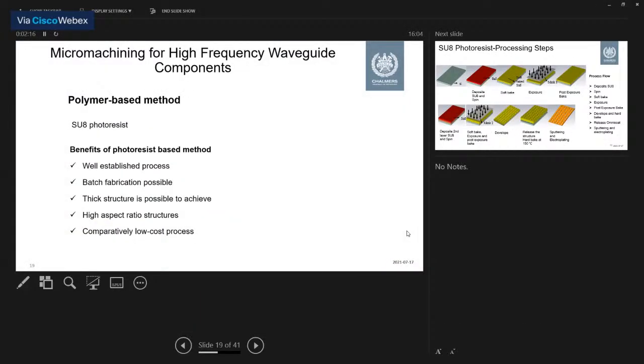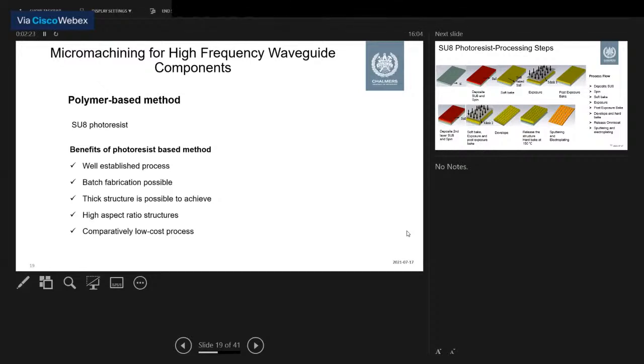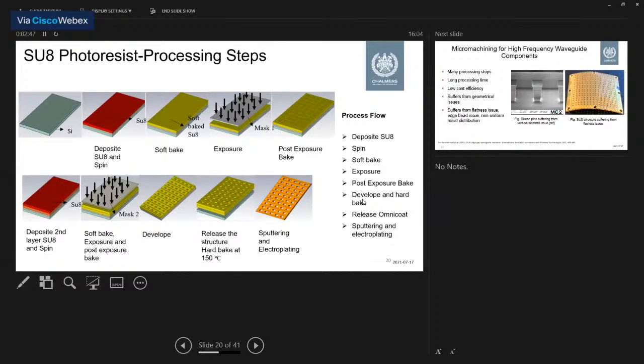If we consider the polymer-based method, SU-8 photoresist is the most commonly used photoresist for very thick structures. The benefit of using photoresist is that it's also a well-established process like the silicon-based method. Batch fabrication is possible. By this method, thick structures are possible to achieve. It can give high aspect ratio structures and, comparatively, it's a low-cost process. These are the processing steps. We need a substrate, and in our case, we use a silicon wafer. We deposit SU-8 photoresist and spin coat it. The spinning speed determines the layer thickness that we need.